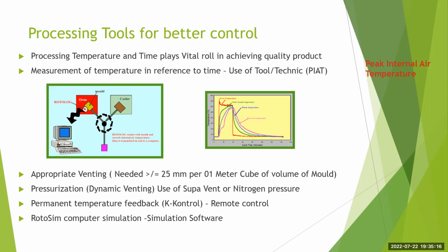The normal thumb rule is that for venting, you need to have 25 mm per cubic meter of mold. You should have a 25 mm vent. But multiple vents are always welcome, so that you don't create pressure in the mold.